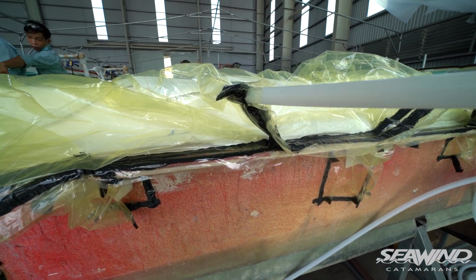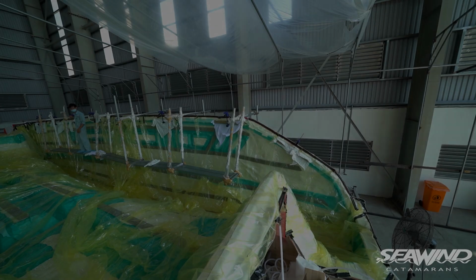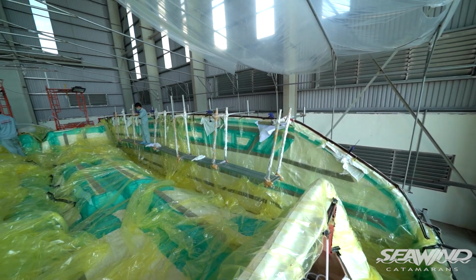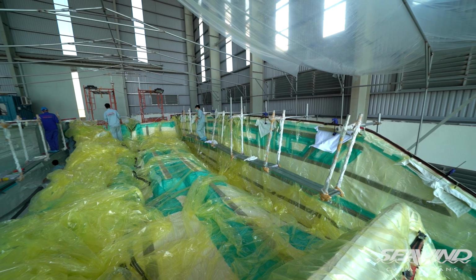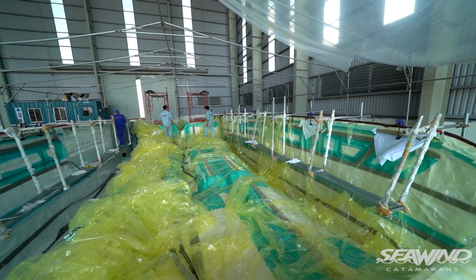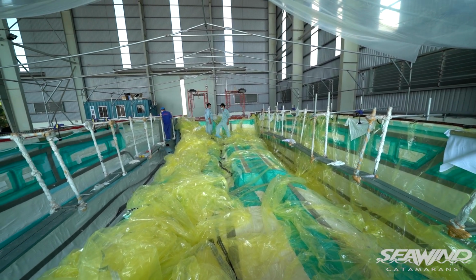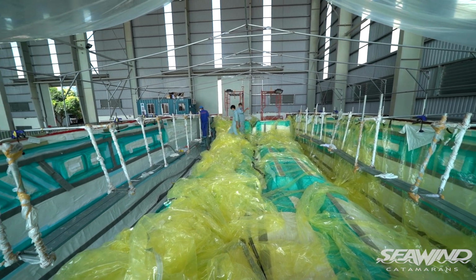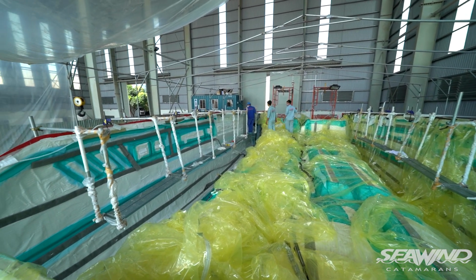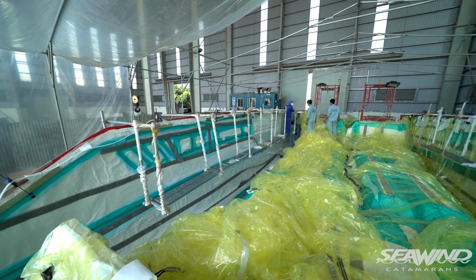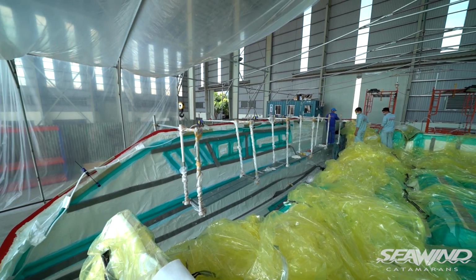This is our most important step of infusion because any air leaks can stop the resin from travelling into the fibres, and the vacuum helps with several things. It secures the laminates in place, compresses the fibres to their tightest bundles, giving a consistent high fibre to resin ratio. It removes any unwanted air voids, and it also helps to boil off any humidity that is trapped in the laminate.